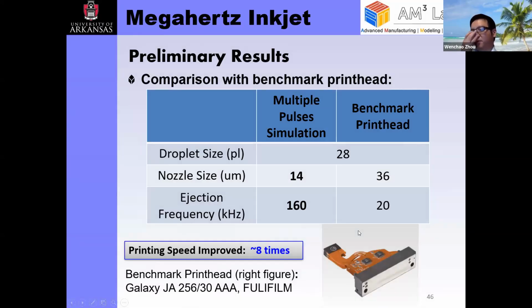This is a benchmark comparison we did to verify that we can indeed increase the printing speed. This is a benchmark printer head we took from an industrial Fujifilm printer head. It uses a 36 micron nozzle size with a 28 picoliter droplet size, and it ejects at about 20 kilohertz, which agrees with our theoretical prediction of the limit of printing frequency. In our simulation, instead of the 36 micron nozzle size, with a 14 micron nozzle size we're able to use multi-pulse to bump up the ejection frequency to 160 kilohertz, which is about 8 times the industrial standard.